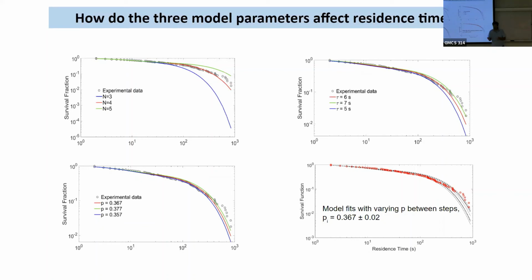Then this one shows how good our fit was, to some extent. The way we fit this is through simulation. We simulate with one set of parameters, look at the fit, and ask whether it is good or not. We calculate the modified R square, then choose the next set of parameters and do this Monte Carlo search process to find the best fit. It's a painful process, especially when in a simulation you're doing a million proteins.